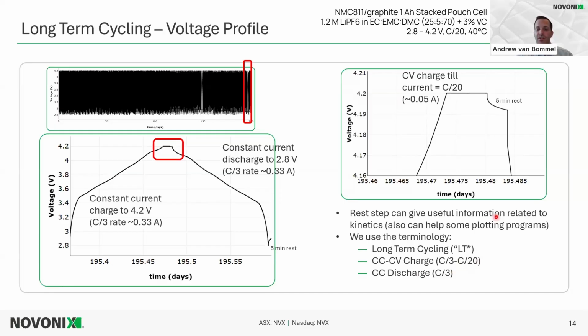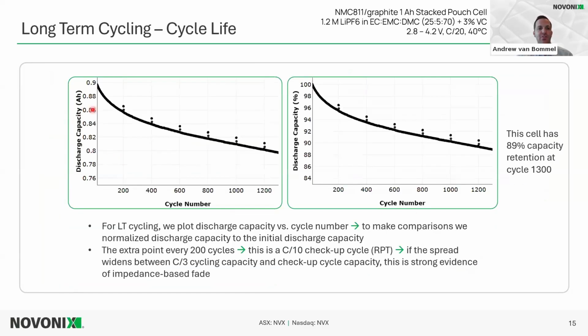And then we report the discharge capacity for each cycle, and that gives you the graph shown here, the cycle life. So here's discharge capacity. This one's starting at 0.9 amp hour, and then ending a little below 0.8 amp hour.